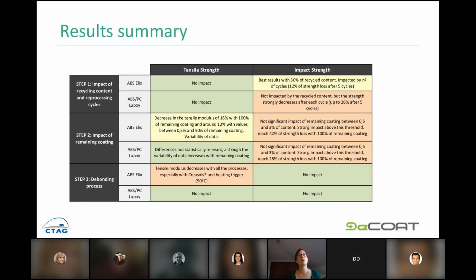So this is the summary of the results. As I just said, the impact strength is the key property regarding the recycled content and the reprocessing cycles, and also the remaining coating, the coating impurities. But it's okay for the debonding processes. And the tensile strength is mostly okay, but has been affected by some debonding systems. Not too much. It's not a very big concern.